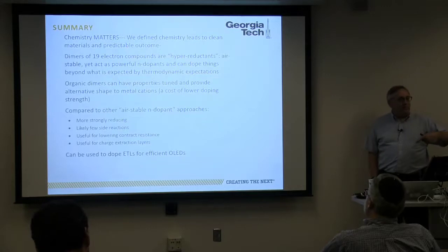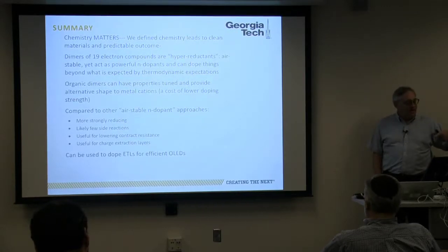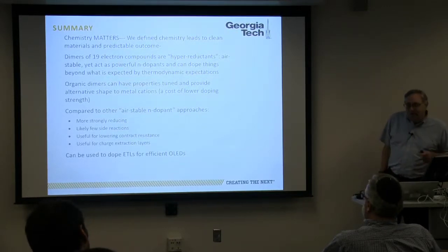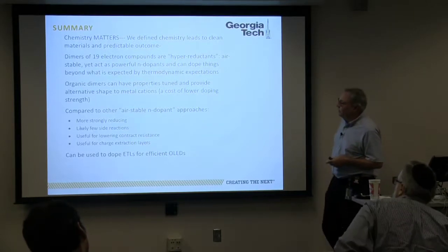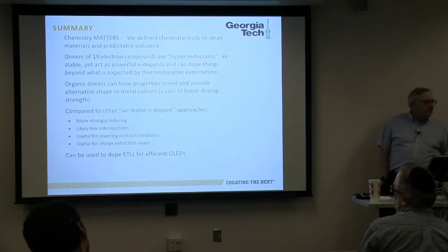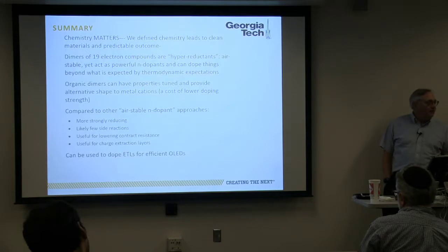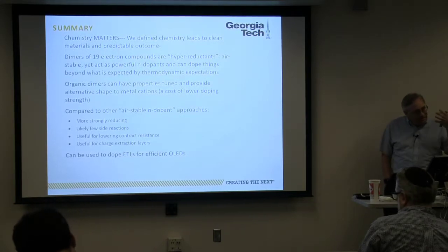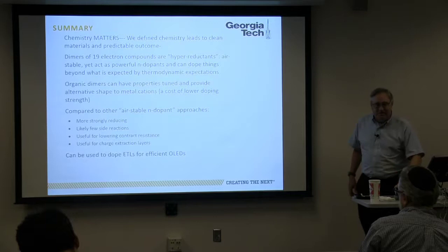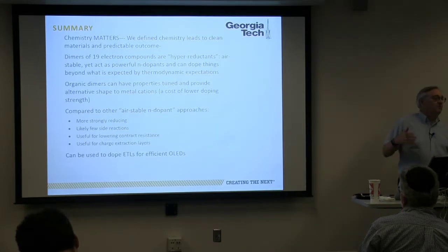We can tune their properties, we can tune the size and the shape of the dopants, and compared to other approaches to having air stable dopants, they're more reducing, they don't have side reactions. And so one of the holy grails for us was to be able to dope these materials for OLEDs, and we've shown that that works, and what we didn't expect was that they would stay doped for a period of hundreds of hours, if not years.